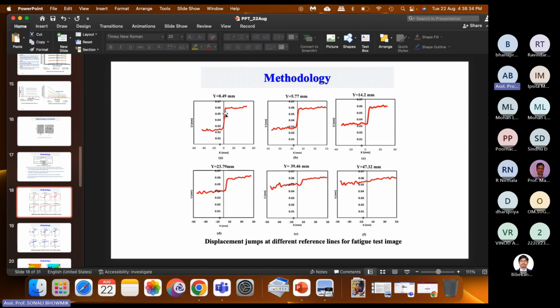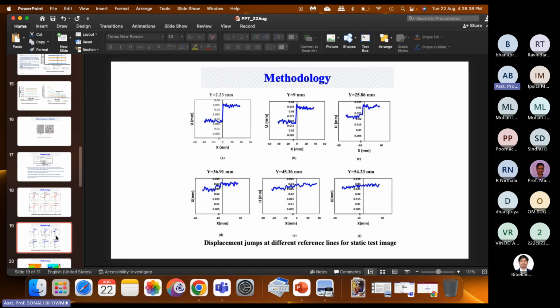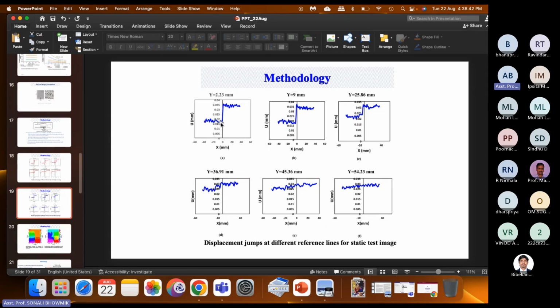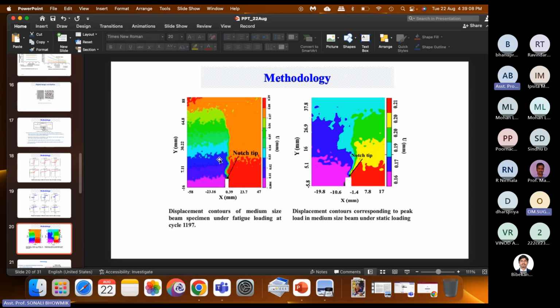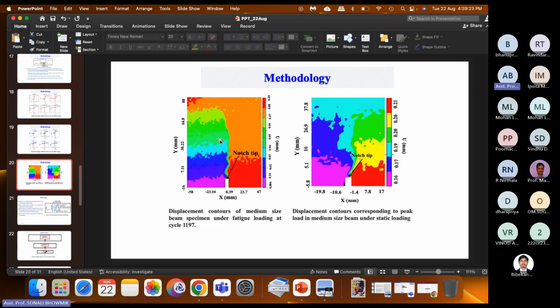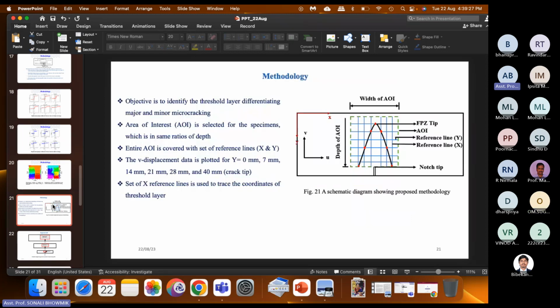So these are two plots. This is under fatigue loading, this is under static loading. This study has been carried out. If you can see both the cases, the same thing was detected: near the crack tip, the opening identified is very large, and when you go upward there is no gradient. So in this work we have named it differently, displacement gradients, which is 0 here, while there is a significant jump near the tip. Now this analysis gives us this type of plots where you can clearly see how the crack is getting propagated. Both plots, one for fatigue and one for static loading. These are the images we are getting, and the data we can get from the MATLAB program.